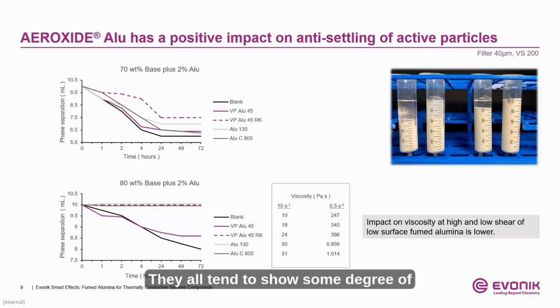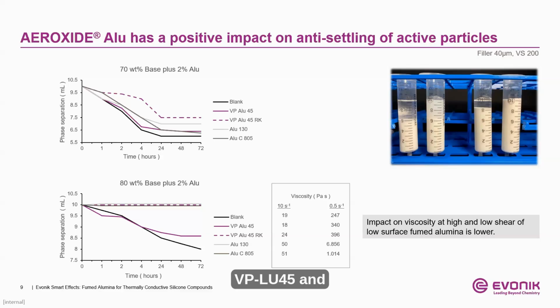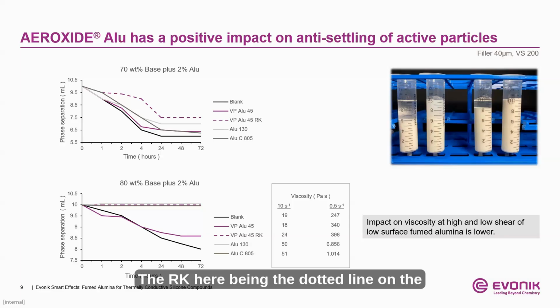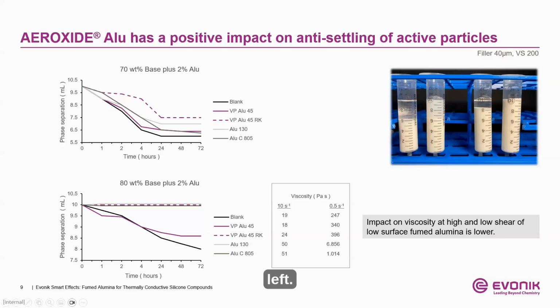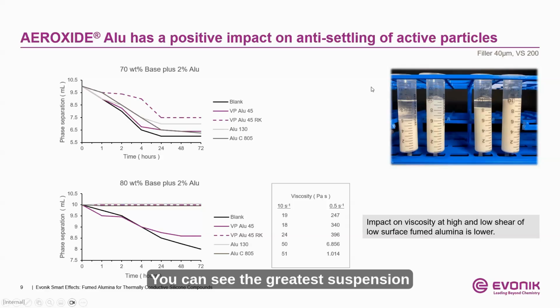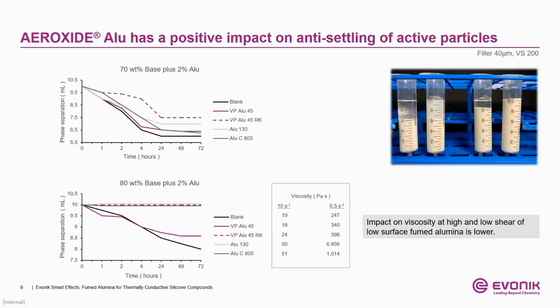As you can see, they all tend to show some degree of phase separation over a 72-hour period. With that being said, there is still a considerable benefit observed versus the blank material containing no fumed alumina, specifically with the hydrophobically treated VP Alu-45 and the VP Alu-45 RK. The RK here being the dotted line on the left. You can see the greatest suspension benefits realized with that hydrophobically treated material.